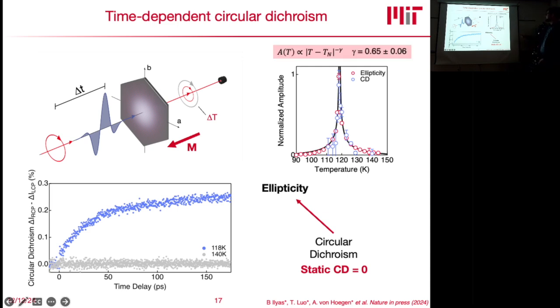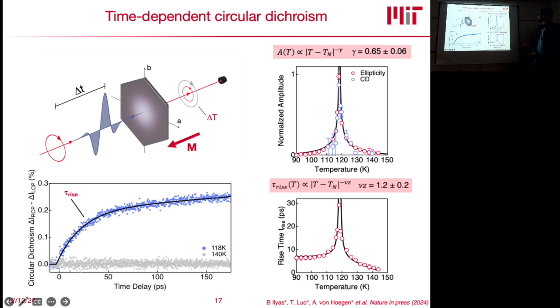And so we can fit this with a power law behavior, and we find a very nice critical exponent, which is compatible with one of the critical groups proposed in this material, a 3D Ising model. Then we can also start looking at the rise time dynamics of this material. How long does it take to establish the state? We also find a critical divergence, again with a critical exponent compatible with a 3D Ising model.